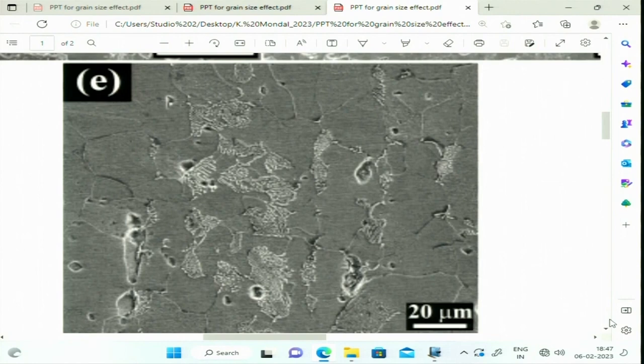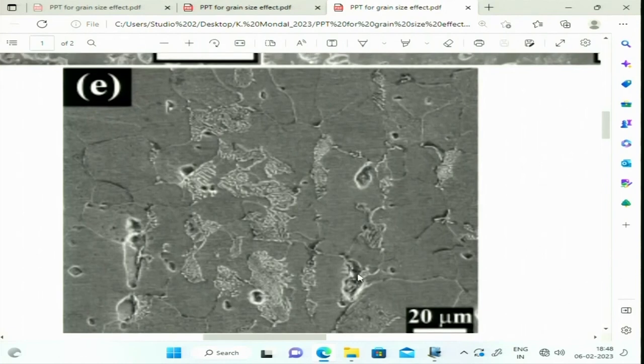And now we have also observed some interesting features. Here we also see pits. So, this is one pit, this is another pit, this is another small pit, this is another pit. Wherever my cursor is moving, you just follow that cursor, you will see those pits have actually coalesced, and then it is forming a kind of deep line along the grain boundaries. Everywhere you could see, for example, here if you see this part, here also it is showing those pit patterns are combined, and then it is forming a kind of a groove.